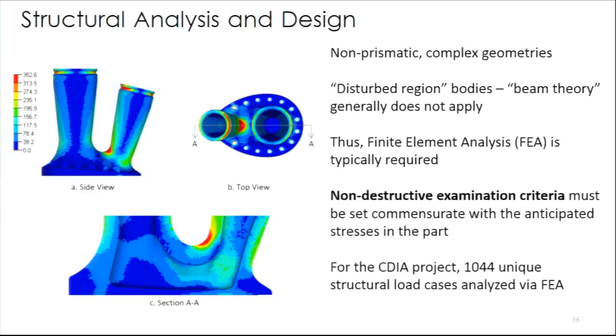For this particular project, we had 32 cast nodes. So at each one of those locations, there's a different set of loading that's applied to it. So ultimately, we had 1,044 FE cases to run and analyze and to consider all of the stresses that were in that joint. And of course, you can't run the finite element analysis until the full geometry of the casting has been determined. And most structural engineers don't have that capability to fully define the geometry of a casting.